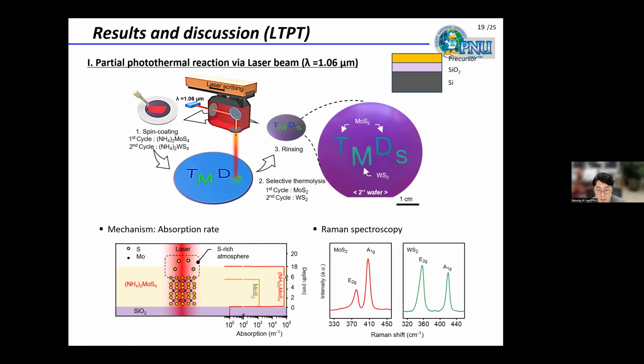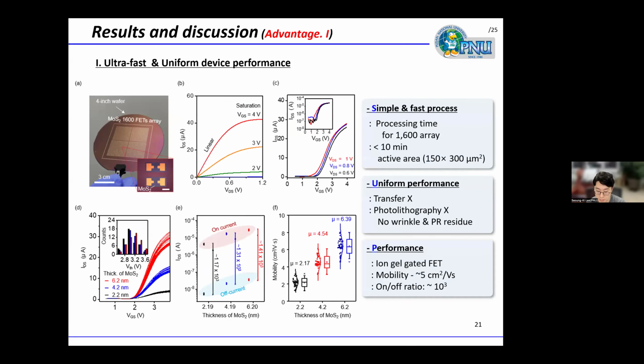smaller than 100 nanometers. Compared with conventional CVD systems, which as you may know can synthesize a large grain size of MoS2, the mobility is quite low, still. But the advantage of this method is that we can get a highly uniform device array. So I try to apply this laser-synthesized material to sensor systems using transistor electronics.